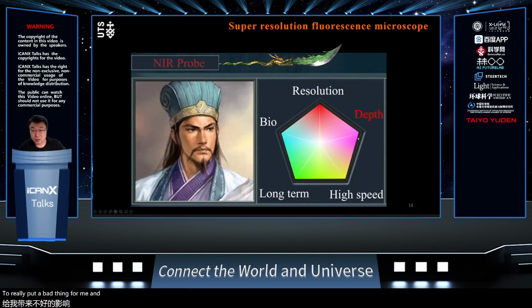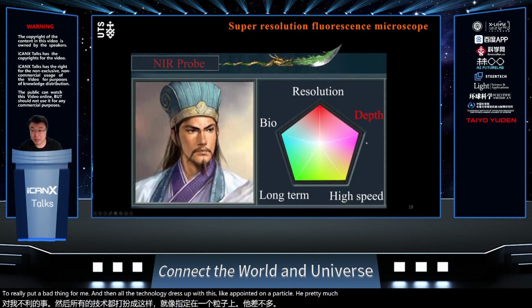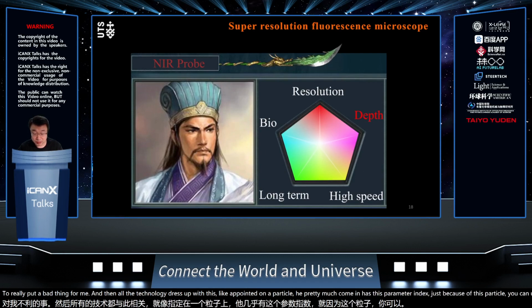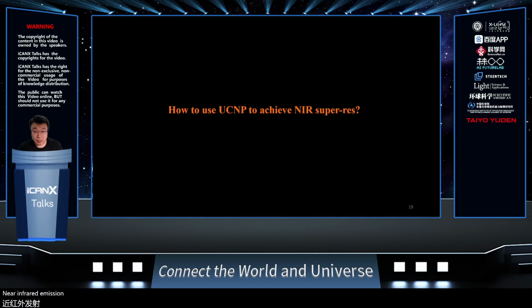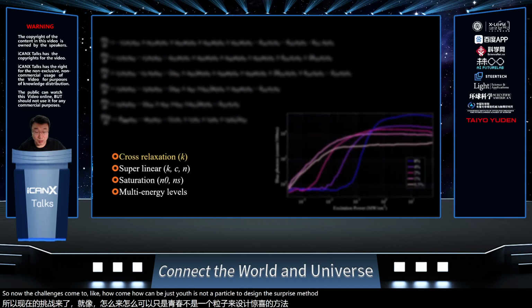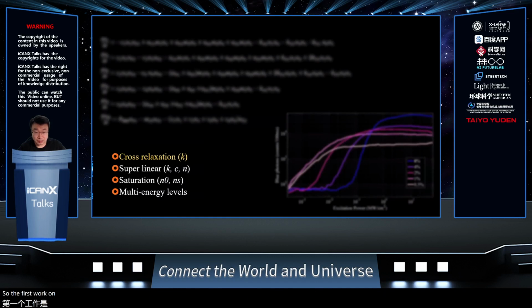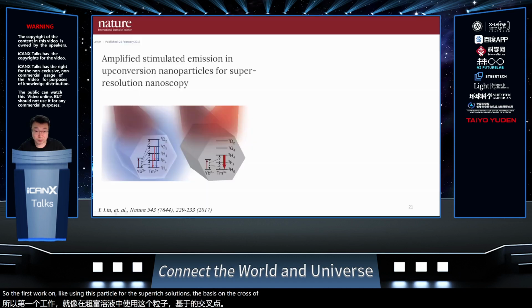And when all the technology is combined with this upconversion nanoparticle, you can enhance the penetration depth, because for this particle you can use near infrared excitation and also near infrared emission. So now the challenge is how we can use this nanoparticle to design a super-resolution method. The first work using this particle for super-resolution was based on cross relaxation, by Professor Dayong Jin's group.